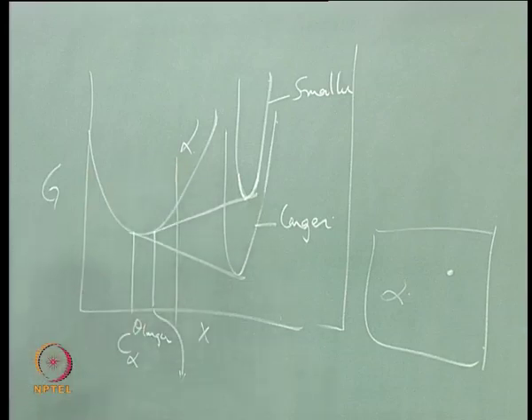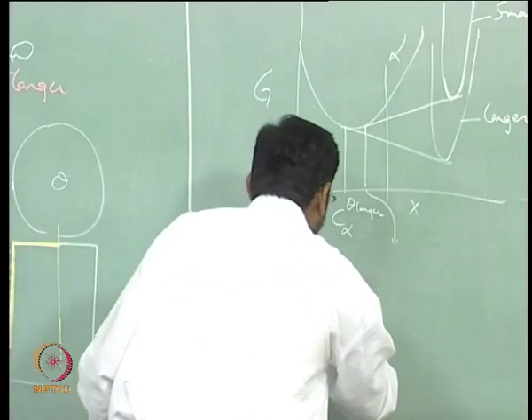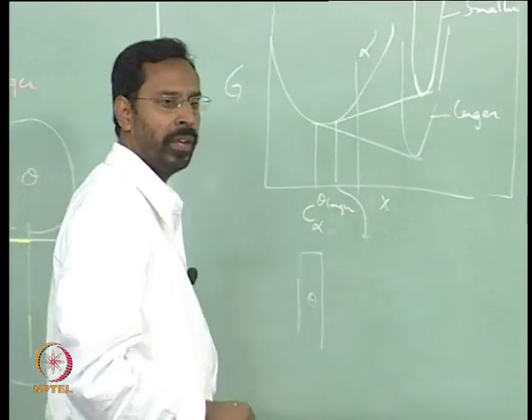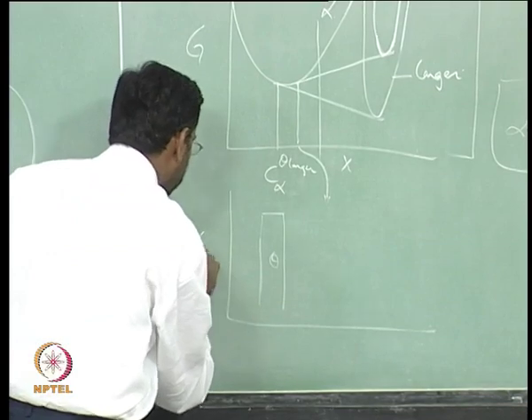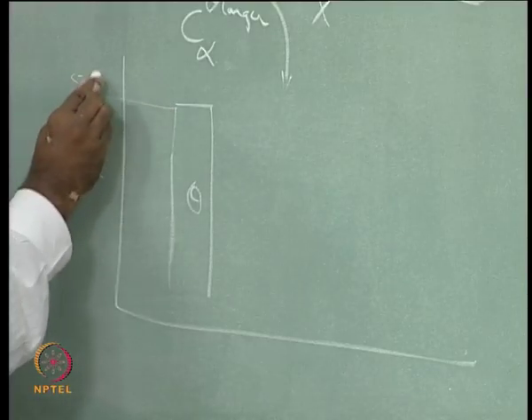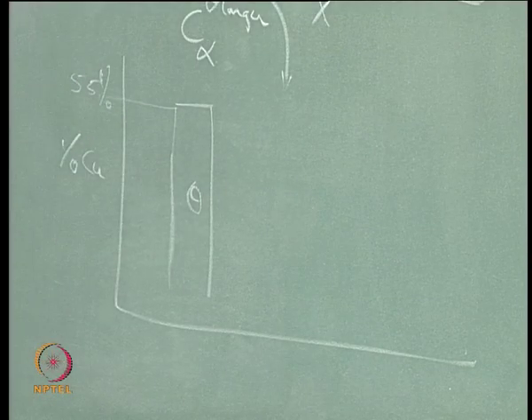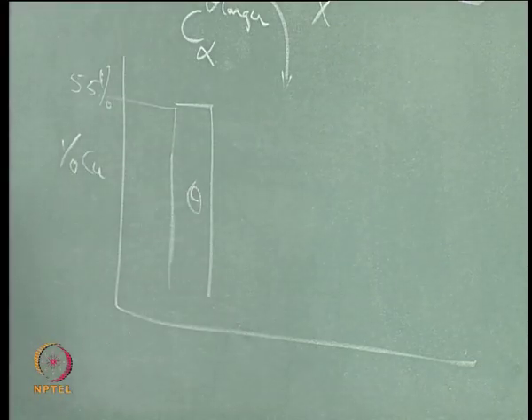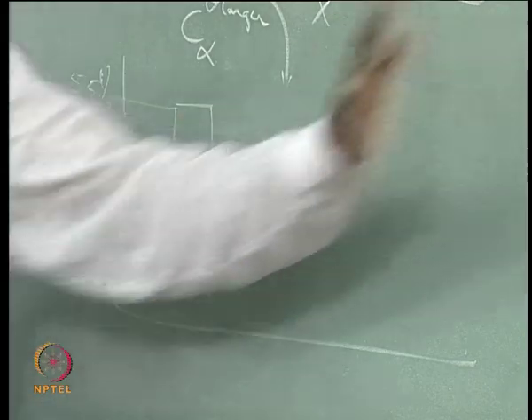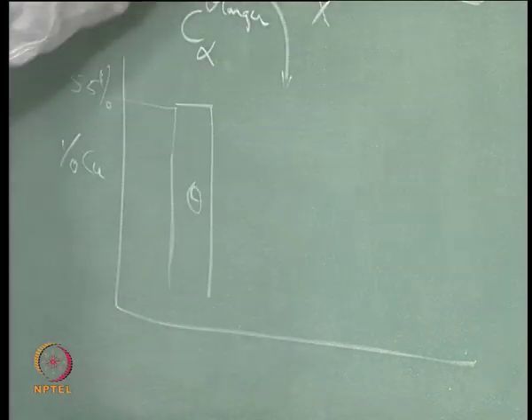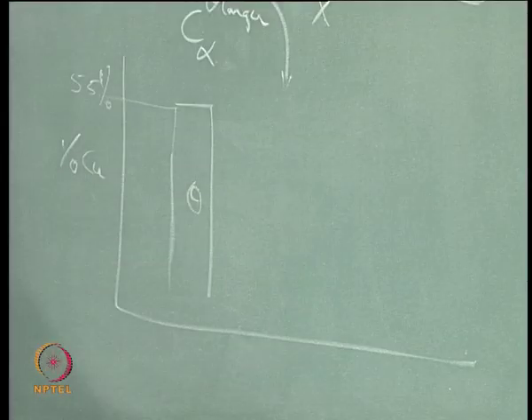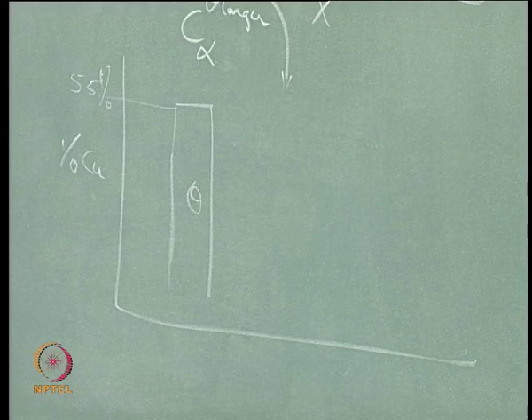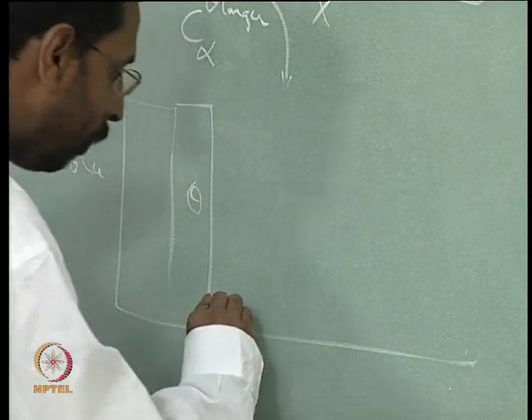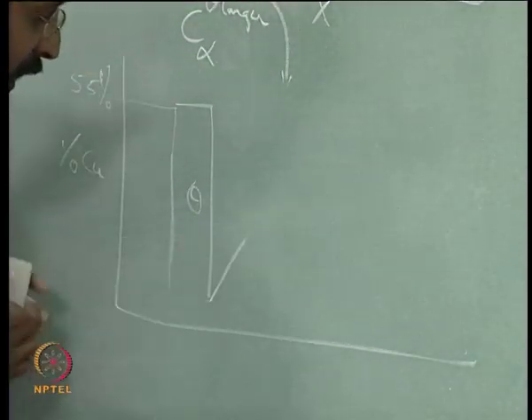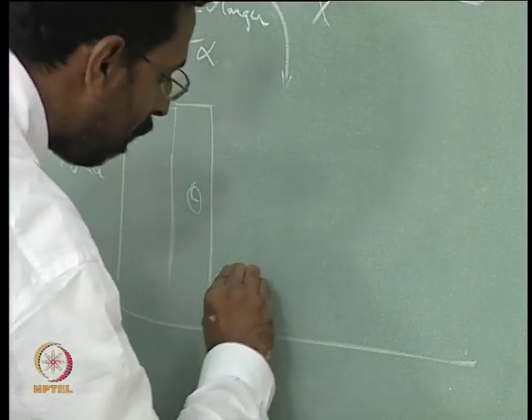and that composition is different from this starting alpha. And as a result, if I now draw again a concentration profile, so if I take a small theta, whose composition, if I plot percentage copper, is again let us say 55%, and has nucleated, the composition of alpha just in equilibrium with theta, that means the alpha composition adjacent to the theta, has a different composition than the alpha composition far away from the theta. The composition of alpha far away from the theta is the starting composition. The composition of alpha adjacent to theta is a different composition, which is lower. Yes, adjacent to theta is a lower copper content. I have really exaggerated it, it will not be like that, because this is 55 and this is actually 4%, something like this.